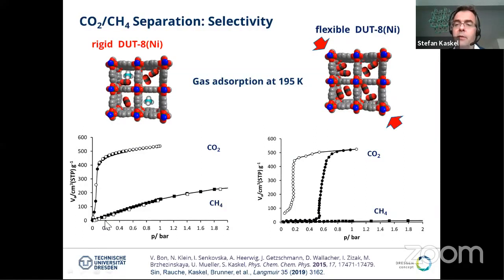And for example, looking at selective gas adsorption of CO2 and methane, many people are interested in separating CO2 from methane, for obvious reasons, because they want to use the methane. In biogases, there's a lot of CO2 and we need to separate it. And of course, in a rigid MOF there's also selectivity because the interaction with the CO2 is stronger. There's a higher adsorption enthalpy as compared to methane. Of course, the boiling points are also different. The critical characteristics are different. So this MOF has already, in the rigid form, a high selectivity for the adsorption of CO2. But no matter which pressure you look at, it also adsorbs methane. And the selectivity will always be limited by the amount of methane that is co-adsorbed.